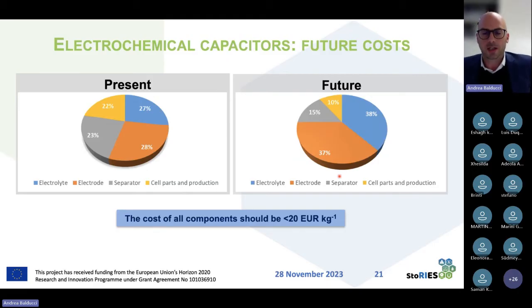What has been forecast, and partially already realized, is that in the future it will be possible to decrease significantly the share of the separator and the cell production, to have something like 25% for the two of them. That, of course, will lead to a significantly higher share of the cost for the electrolyte and the electrode. And what will be extremely important is that in the future, the cost of all components should be less than 20 euro per kilogram.